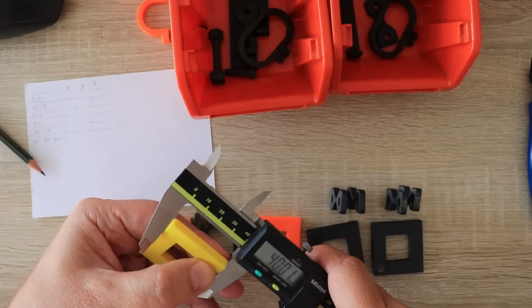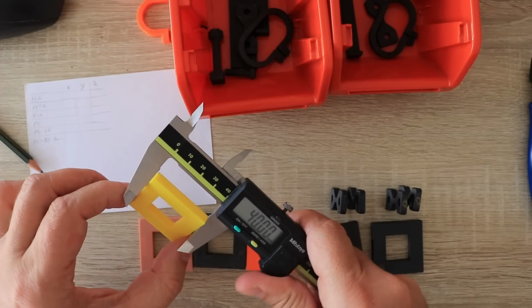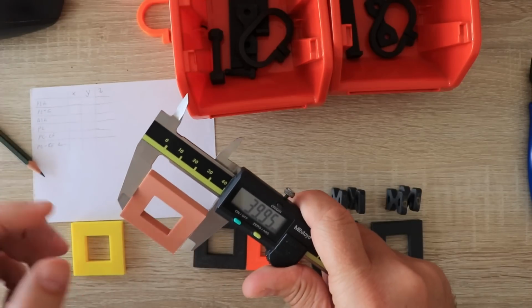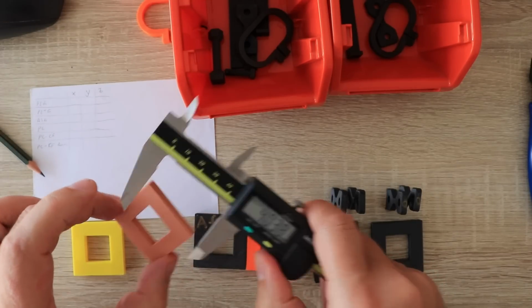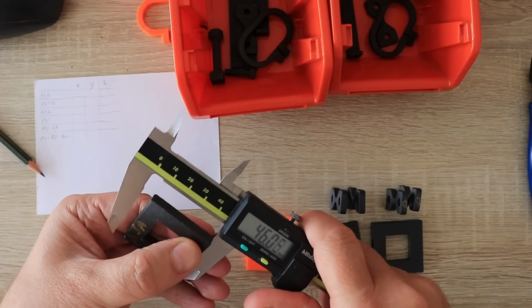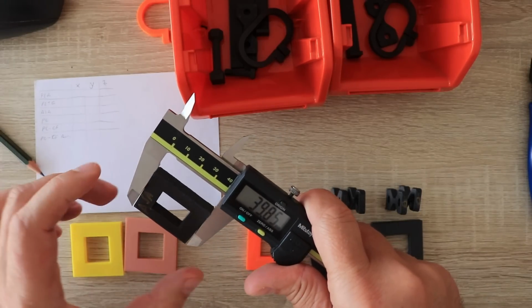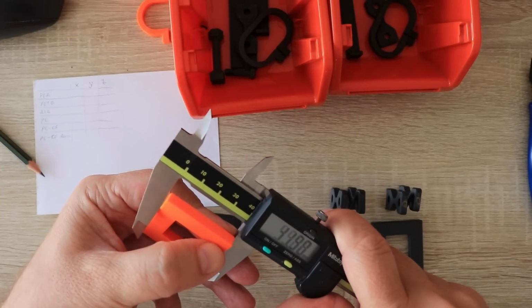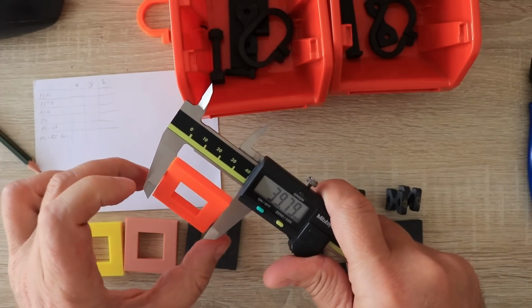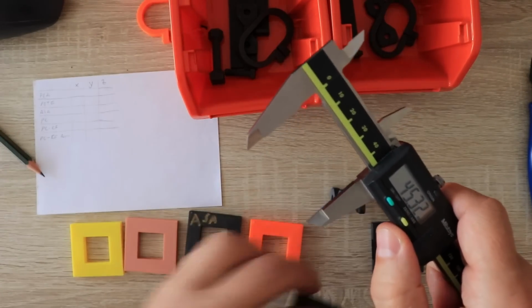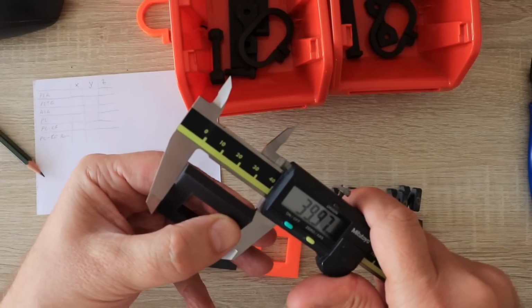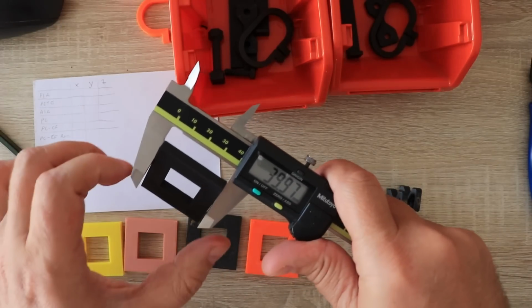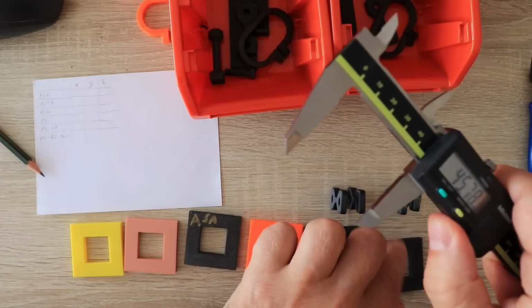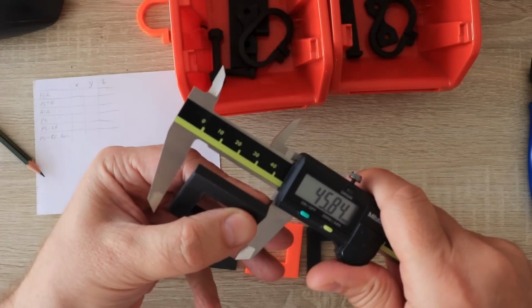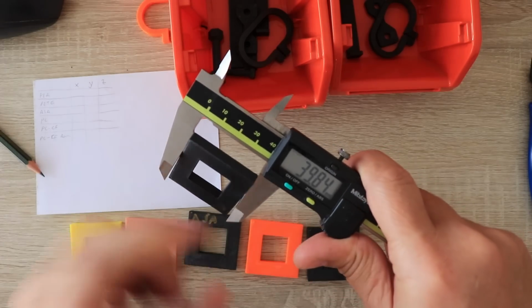This dimension should be 40 millimeters. Then PETG, and then ASA shrinks a little bit more than PETG. From these objects, the regular polycarbonate should shrink the most. And this is the carbon fiber version of the polycarbonate, and as you can see it is very close to that nominal value. And this is the annealed, and it should shrink less than 1%.